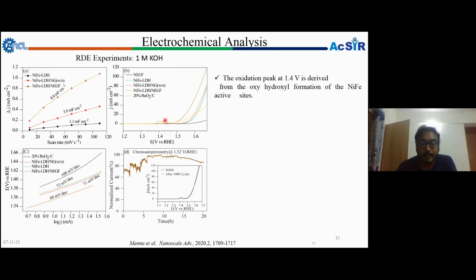The second thing is how long it can sustain. As you can see, the overpotential is around 1.2 volt, because this is a comparable value to solar to fuel formation. Here 1.52 is the onset potential, from where the oxygen evolution reaction starts. So at 1.52 volt we kept it for a long time to see how long it can show the oxygen evolution. Here you can see it shows the oxygen evolution reaction for almost 20 hours.